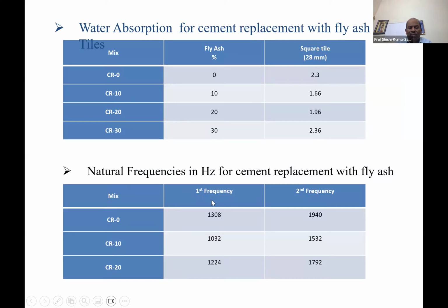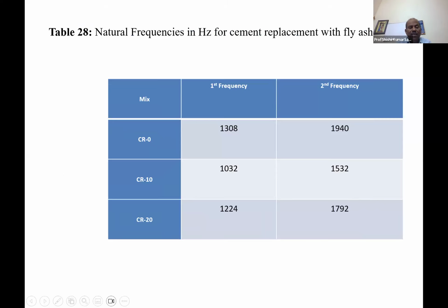So what we do actually, you know that I work in dynamics. So we have the FFT analyzer, so we have tested it. We saw that this gives an indication of the stiffness. So as you add fly ash, the stiffness goes on decreasing. But the second frequency here is increasing, but less than the normal.